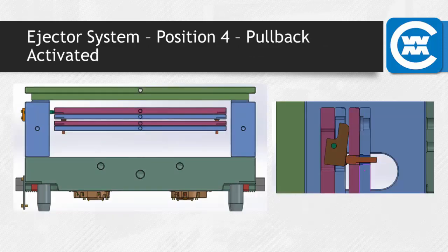A little bit before we get there, we end up in the pullback activated position. So at this point, you can see the plates return and that we've almost gotten back to position 1, but plates 1 and 2 are still separated. But you remember those return pins that we discussed earlier and we said we would mention it a little bit later? Well, now they come into play. They aren't shown here, but as the die closes, they contact the other half of the tool and push that little gap together between plates 1 and 2 and 3 and 4. So then we end up back at position 1 before we start the next cycle and we're ready to make a shot.